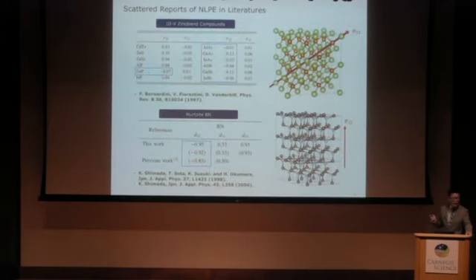There were actually scattered reports. I think this paper was from David's group. They looked at the piezoelectric coefficients for some III-V zinc blende semiconductors. As you can see, quite a few of them have, even though small, negative e33, in this case along the 111 direction. It turns out wurtzite boron nitride has a pretty decent negative d33, reported in these two papers.